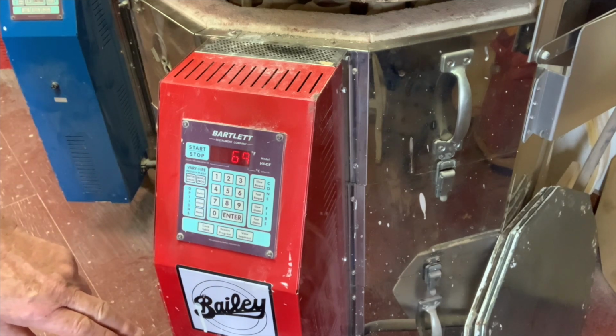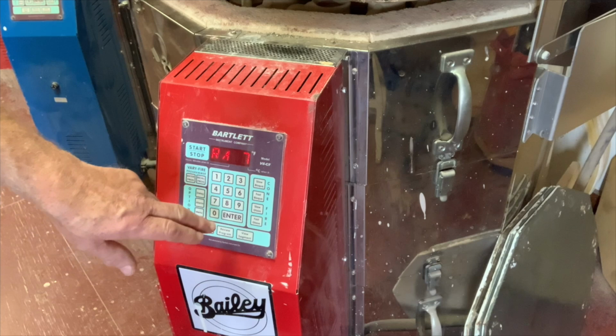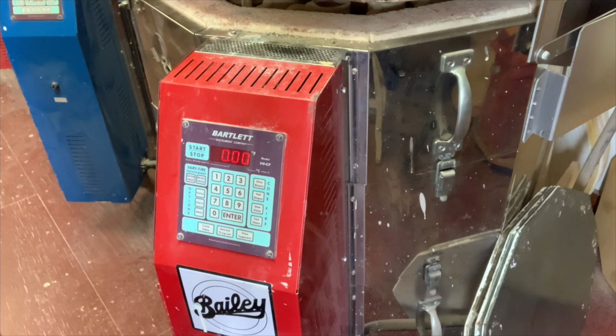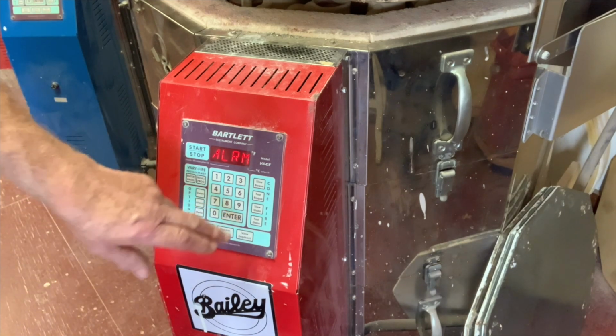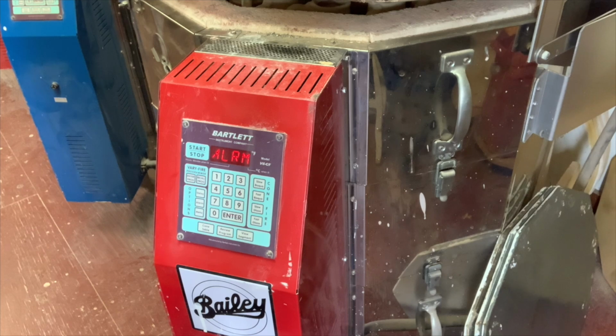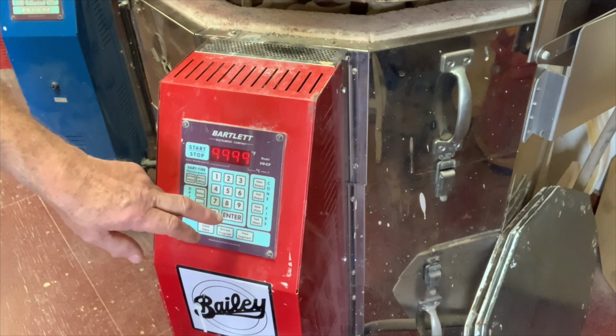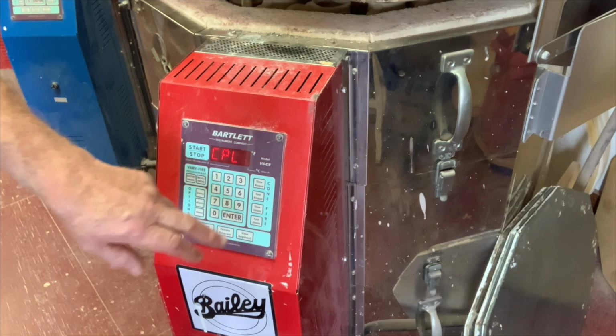And then the last bit is 69 degrees down to 1700 and no hold. So that's a slow cool, and then enter the alarm 9999. You don't need that. The reason I do that is it's a slow cool program to enhance crystal development in the glazes. So natural cool from peak temperature 2225, which is a little below cone 6, which is 2232.